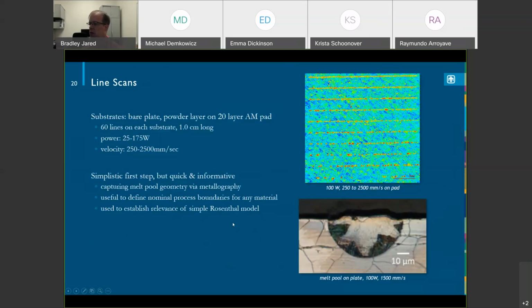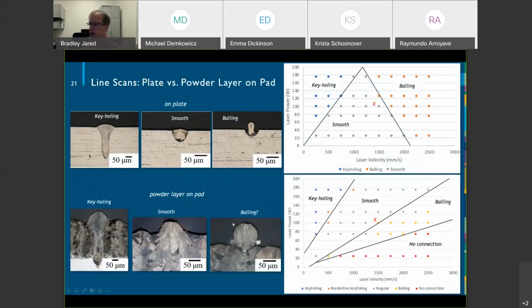And actually, I have this slide. Yeah, so here's some results. You can see some of this where we're doing it on the plate again, so there's no powder on this. It's super simple and easy to do. You don't even have to have your machine necessarily. If you have a laser scanner that's similar, you wouldn't even have to do this on a machine, but you can capture these keyhole events, or a nice good melt pool, or something where you get balling where you're not going to get good material adhesion. We then can also translate that and do it on a pad, a little more work, not a lot, and we can do the same sort of thing. You'll see the trends are slightly different, but these are great starting points.